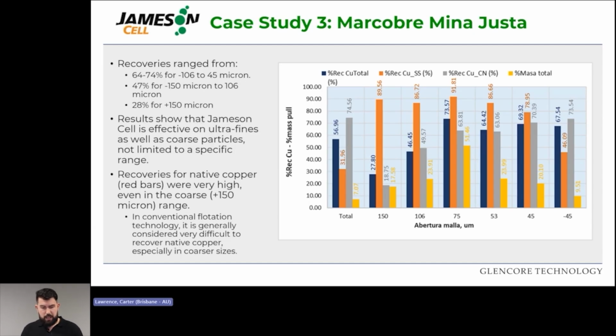Now, an interesting addition for Mina Justa was, you can see on the red bars on the graph, the recoveries for native copper were very high, even in the plus 150 micron range. Now, in conventional flotation technology, so a standard tank cell, it's generally considered very difficult to recover native copper, especially in coarser sizes. So this was a somewhat unexpected surprise. And was very welcome, of course.